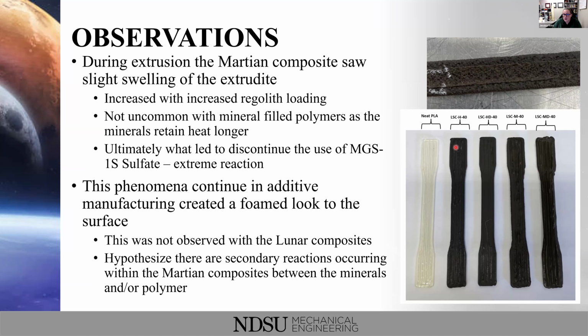Interestingly enough, we did not see this on the lunar parts, right? So this is our neat PLA, and then all of our 40 weight% filled polymers. And they have really nice surface finishes, right? You can see some of the raster lines here in our 3D printed parts, but for the most part, they looked great. And so it's really an issue with our Martian simulants, and they do have different minerals than the lunar simulants do themselves. And so we believe there are some secondary reactions occurring within our Martian composites.